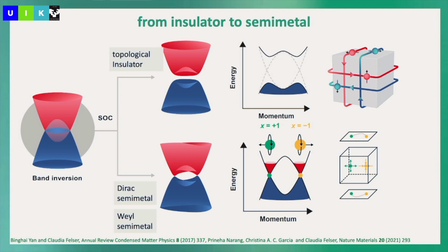But recently people were very much interested in looking for similar materials like we know from graphene. If certain rotation symmetries are protected, for example, then we can get semimetals where we still have this linear dispersion and these crossing points. Depending on where in our electronic structure this position is, we can have Dirac or Weyl semimetals. If you have simply the Dirac equation, you can have 2 different special solutions. One is with the higher symmetry, the Dirac semimetals. This is a 4-fold degenerate crossing point. And in Weyl semimetals, you have these points at low symmetry points, which means it's also much more difficult to find because it's not so obvious to see in the electronic structure.